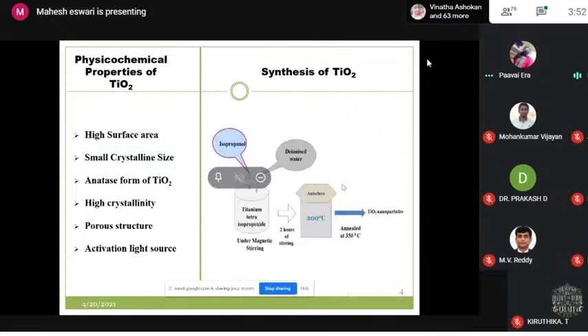Now, the synthesis process comes here, where you can see the titanium tetraisopropoxide. This is the starting precursor. Along with isopropanol and deionized water, it is stirred in a magnetic stirrer for 2 hours, and then it is transferred to an autoclave and maintained at 200 degrees centigrade.